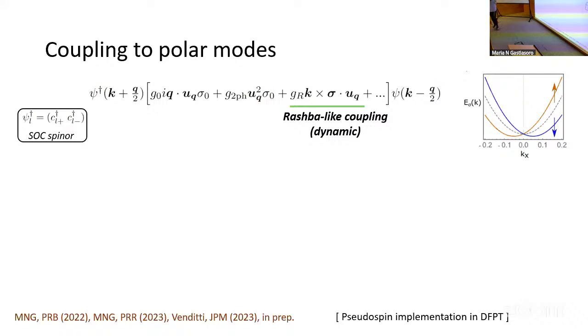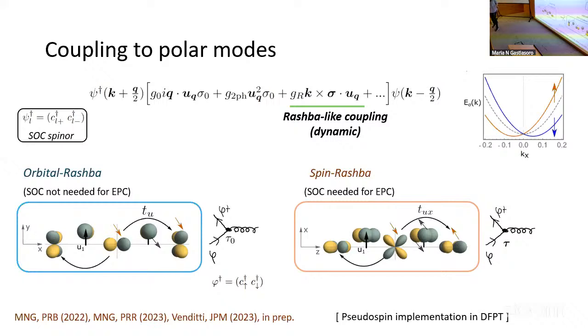Okay, so the first thing that we did was, okay, this is allowed by symmetry. How do you get it in these systems? And we showed that the spin-orbit coupling enters to some extent, but it's not directly proportional to the coupling. And so you can have something called orbital Rashba or spin Rashba. And this, as often happens, led us to realize that some tools in the toolbox were missing. There was some extra implementation that needed to be done, and so on. So the take-home message from this is that the coupling to these modes is highly non-trivial. Okay, and it's linear in k.